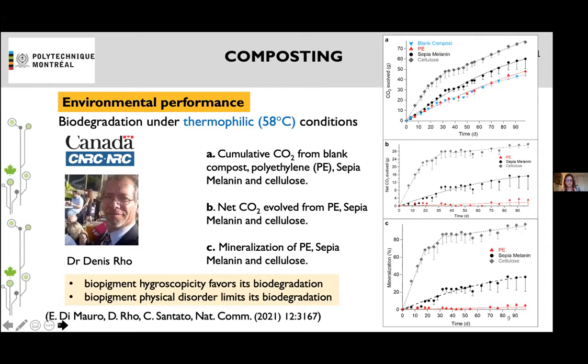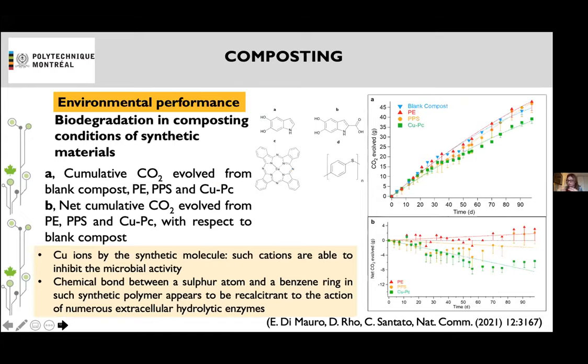And we think that this somehow promising behavior is due to the hygroscopicity of the material, which facilitates the access of the enzymes to the material itself. Of course, we should try to improve this performance, and I'll tell you what we are going to do to go from this 40% after 90 days in industrial compost and increase the mineralization rate. It is also interesting to know that if we compare with organic electronic materials that come out of a synthetic lab, we behave much, much better. For instance, copper phthalocyanine or the conducting polymer PEDOT:PSS do not degrade even if they are organic, and actually they have an inhibiting action on the process, at least in the case of the copper phthalocyanine.